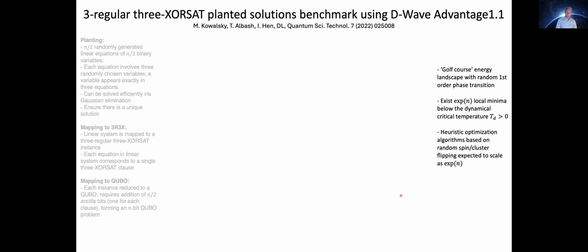Next, and this will be the last of the negative results, we looked at three XOR sat planted solution problems. So these problems, they have planted solutions. So that means that we knew the answer in advance. The ground states were known in advance, even though these are very hard problems if you don't know the answer in advance. In fact, they have a golf course type energy landscape. There are exponentially many local minima below a critical, the dynamical critical temperature, which is greater than 0 for these problems. And basically, heuristic optimization algorithms that don't know what the answer is are expected to scale exponentially, and so take exponential time for these problems.